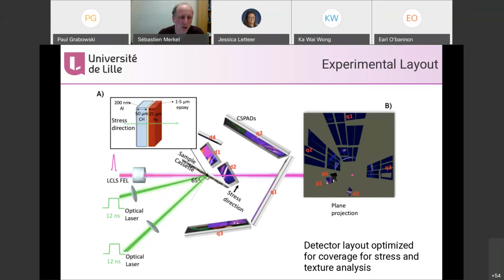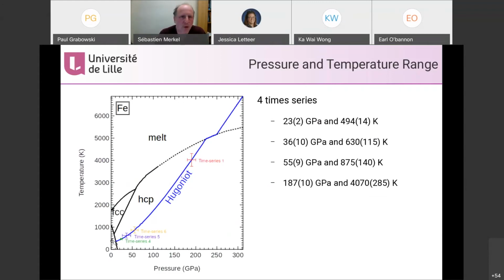And then the FEL beam was launched at 65 degrees relative to the shock direction to allow something that looks like what we call radial diffraction, for instance, in diamond anvil cell data. And this is why I was called in, for my ability to process this type of data. So we have 4 pressure and temperature ranges in this set of experiments. I will be mostly speaking of this one here, where we have results at nearly 2 megabars and 4,000 Kelvin. And then we also have results in the lower pressure range between 20 and 55 GPa.